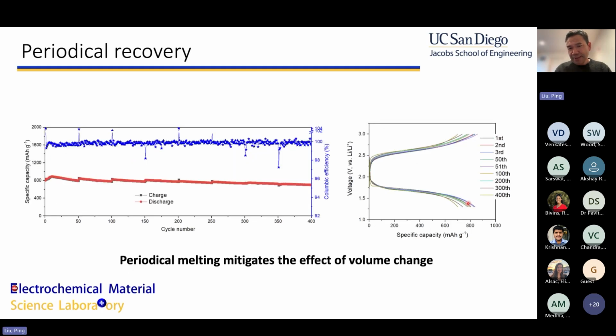Now, the final proof is our proposed mechanism: if the batteries start degrading because there's still volume change, can we reheat and reset the structure? And the answer is we can. So over here, you see every 50 cycles, when the batteries start to degrade, we warm it up and then we remelt it, and then the impedance will drop.